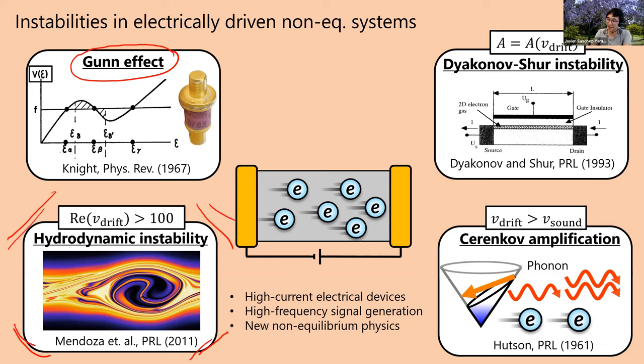And what we actually ended up seeing is the following, which is this effect known as Cherenkov amplification, which is another effect which actually had never been seen before in a 2D material, but has been seen in semiconductors a long time ago, where if you drive an electronic system to a high enough drift velocity, it can start to spontaneously emit phonons. It's an effect similar to Cherenkov radiation of light, this is a Cherenkov radiation of phonons.